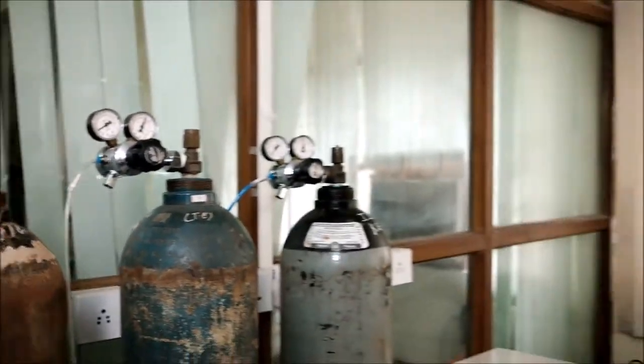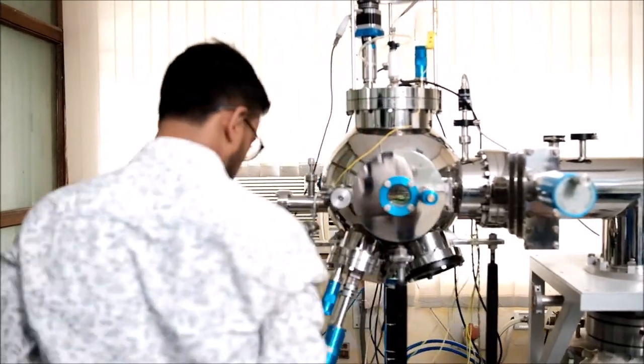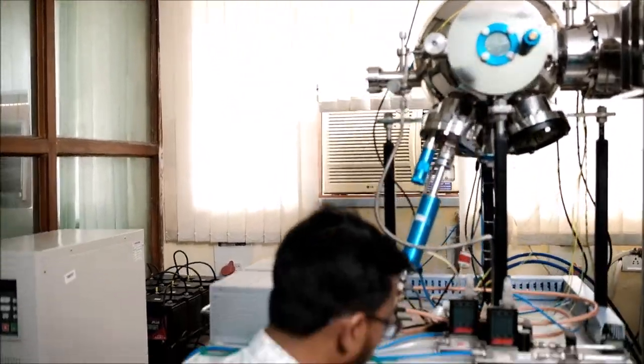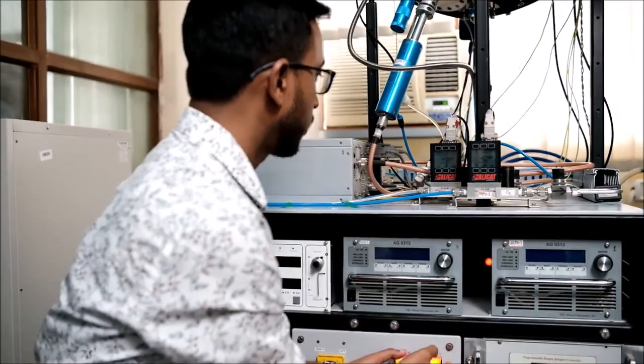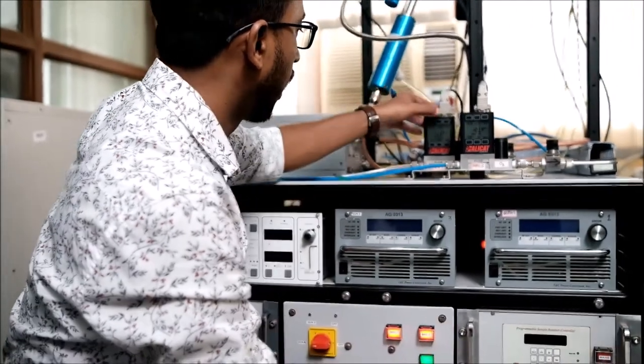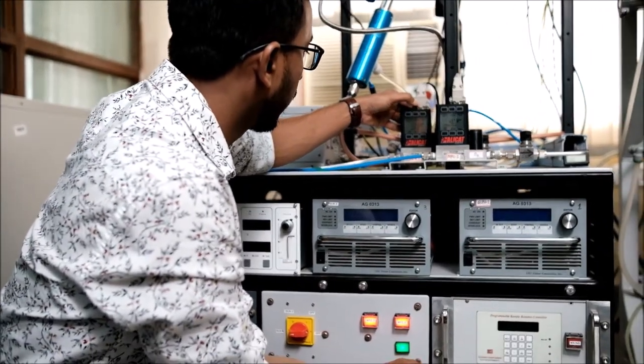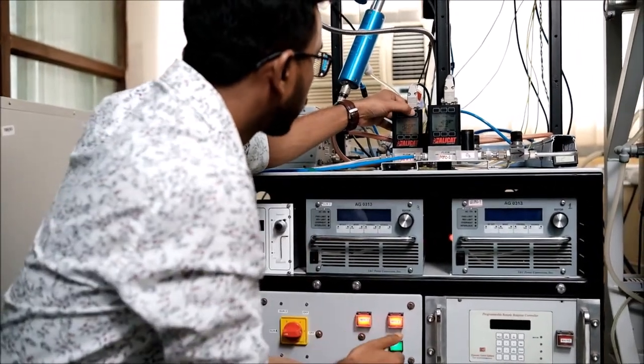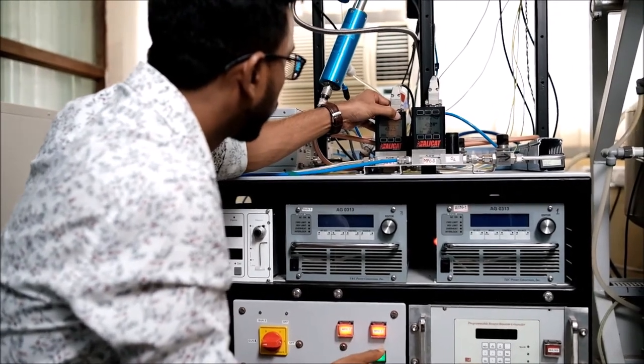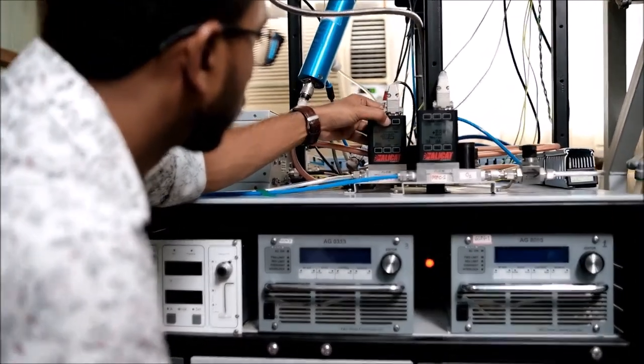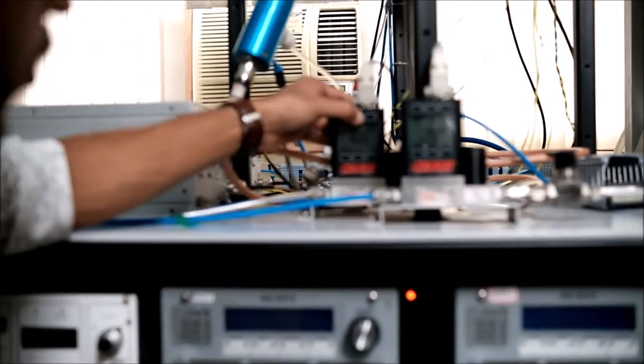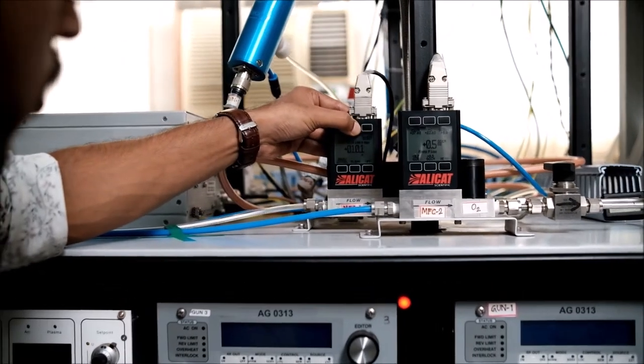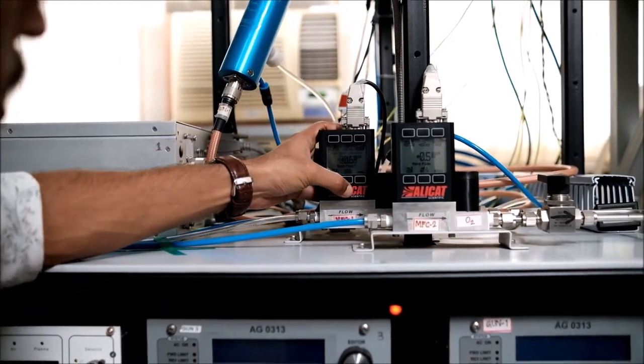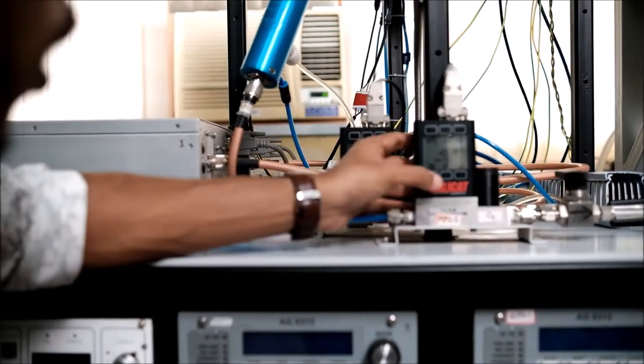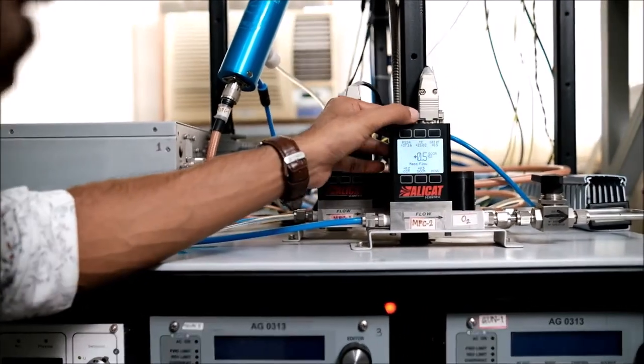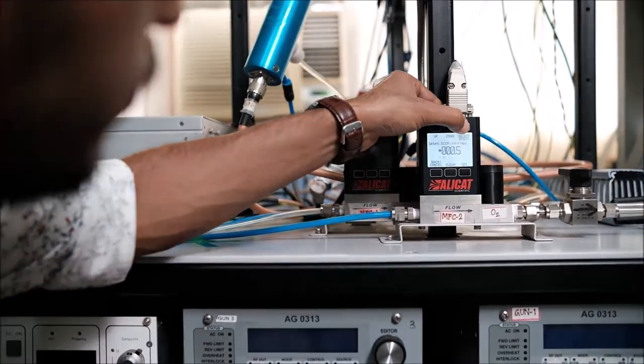Both the gases are coming out from the gas cylinders. Now I start on both of the MFCs. And I'll set the argon for 10 SCCM flow. So the set point, then, yeah. And oxygen I will set it to 1 SCCM.